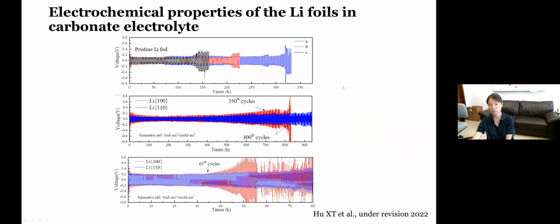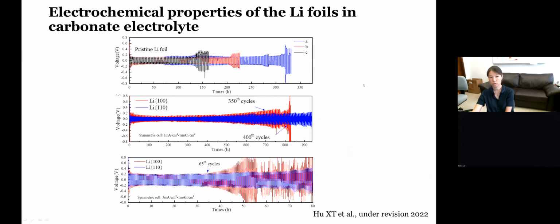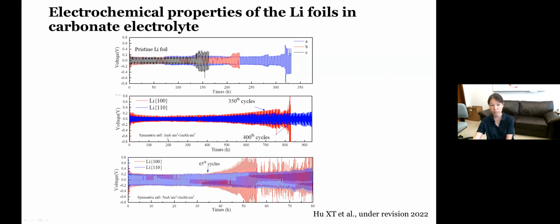Now, the important part: how do the electrochemical properties relate to all these different samples? And again, for the pristine samples, we have a number of tests, right? For each of the cells assembled with the pristine lithium foil as the electrode, we obtained somewhat different behaviors. At the very beginning, we thought this must be because we were not technically proficient. So we tried many times, but we still saw a lot of variation in the lithium foils. With long-lived ones, you can cycle at 1 milliamp per centimeter square with a capacity of 1 milliamp hour per centimeter square. This lasts to about maybe 300-something hours, right? But with very short-lived ones, only tens of hours.